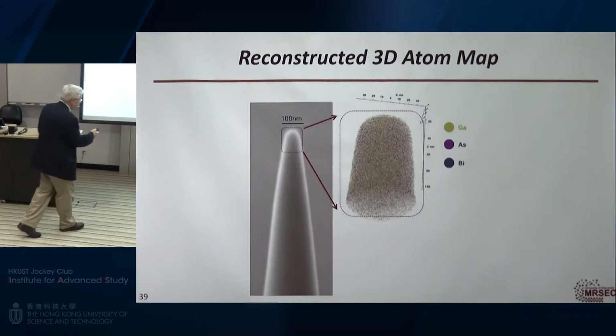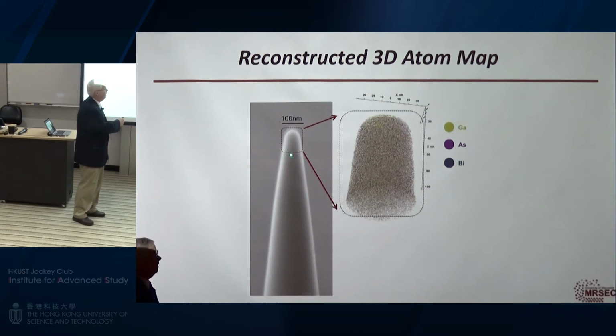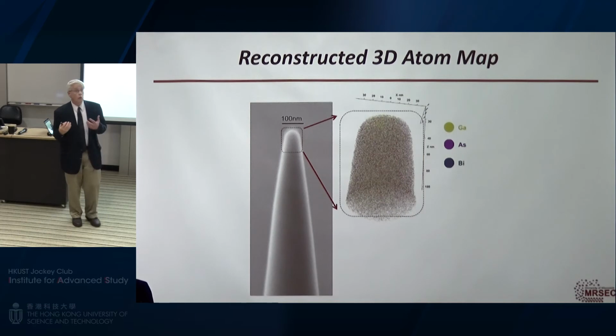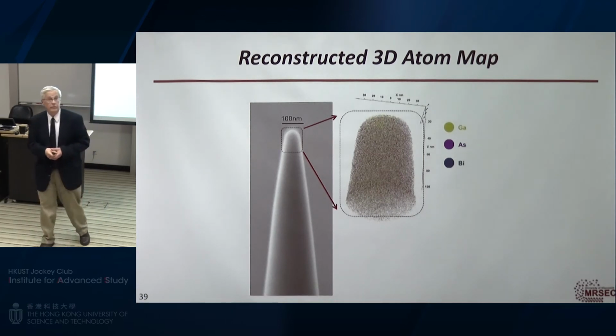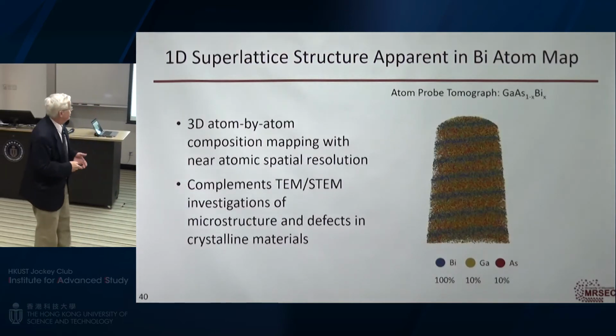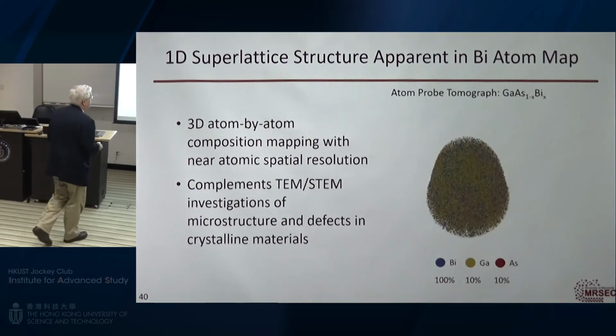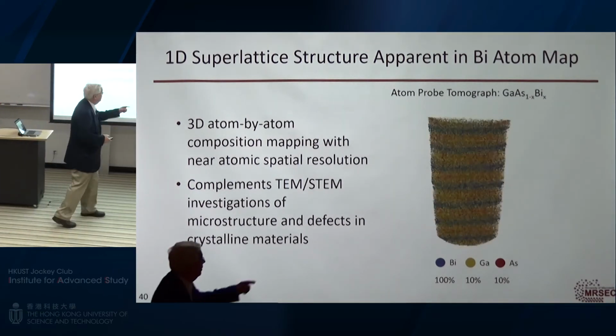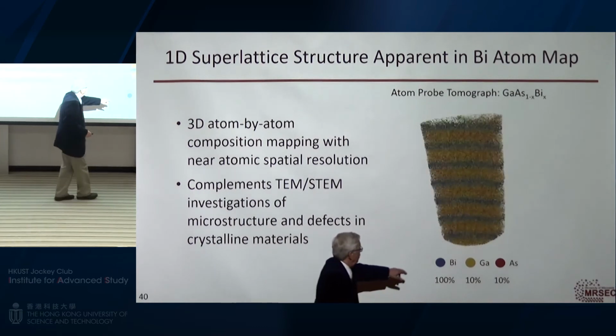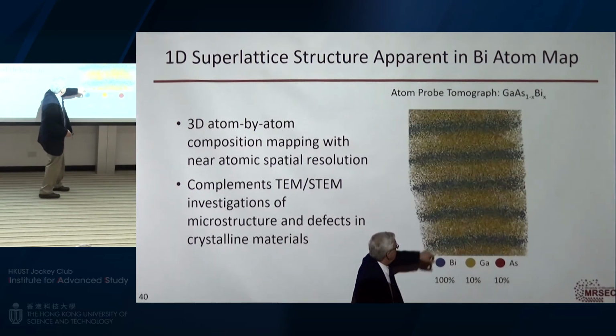Which means I can decompose this tip one atom at a time and reconstruct it in a computer to actually see where all the atoms are inside that crystal. And if I do that, you get something that looks like this. This is that tip, and you can see where the bismuth is and where the gallium and arsenic are.